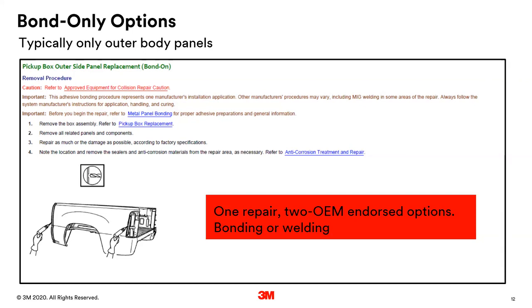So I guess the answer here is that the 3M adhesives that we're talking about here today operate in a wide range of temperatures, okay? The key caution temperature would probably be getting too cold, right? So if you get down below 40 degrees, it basically shuts off the chemical reaction. So you don't want to apply it or use it in a really cold environment, okay? It's going to take much longer to cure. And again, below 40, it may never cure, okay?